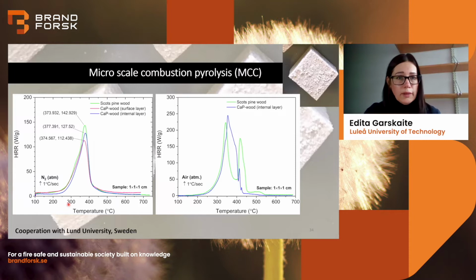So MCC data. Here we have cubes, and what we did actually was microslice those mineralized wood specimens, and we recorded from the surface and from the middle of the wood block. And we also compared that with a reference wood. We did analysis in nitrogen atmosphere as pyrolysis conditions, and also in oxidative conditions, in air. So let's see what we have here.